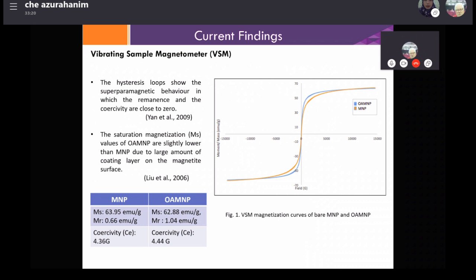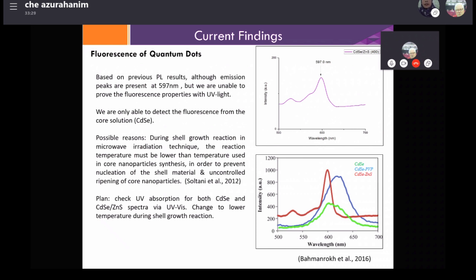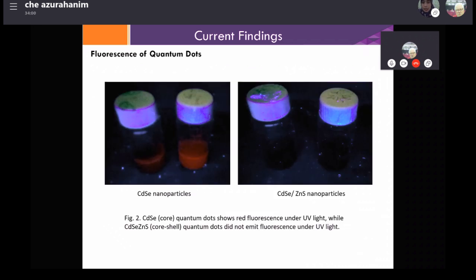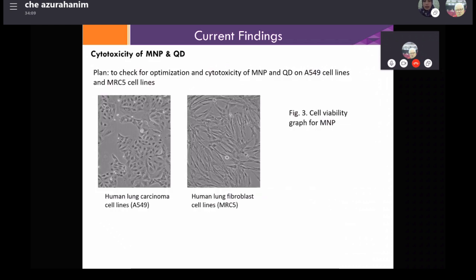My student also did fluorescence of the quantum dots, where currently she's planning to check the UV absorption for both CdSe and CdSe/ZnS spectra via UV-Vis. Basically, she was only able to detect the fluorescence from the core solution, that means the CdSe. So we still need to figure out several problems that currently occur. Here are the images for the CdSe nanoparticles as well as the CdSe/ZnS nanoparticles. My student also did MTT and LDH assays to check for the optimization and cytotoxicity of the magnetic nanoparticles and quantum dots on lung cancer, which is the A549 cell line, as well as the MRC5 cell line.